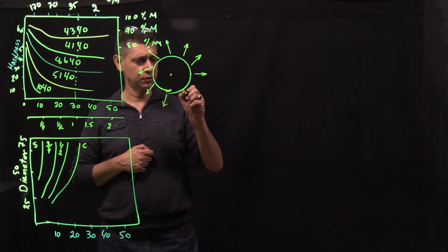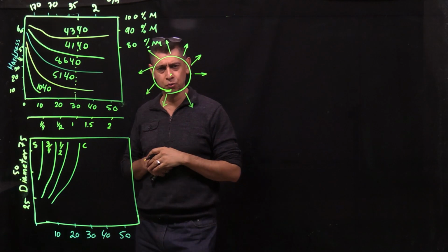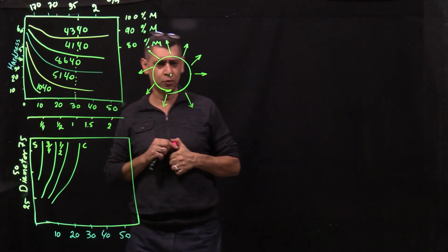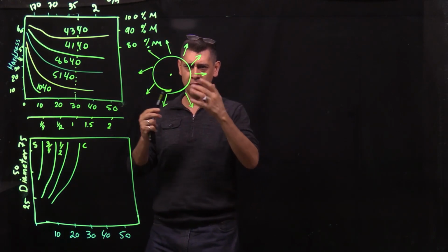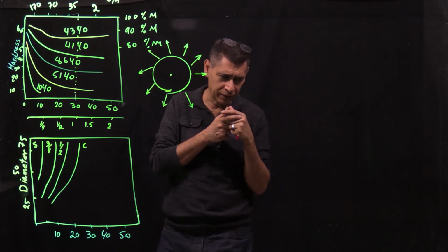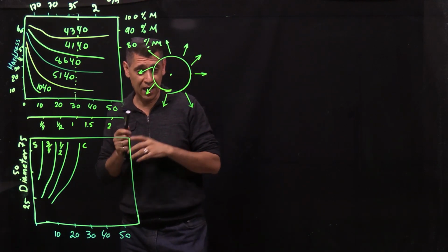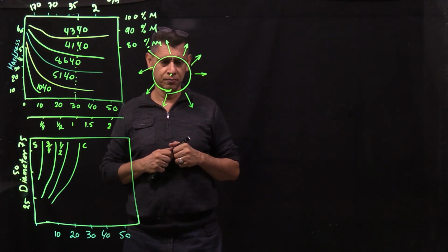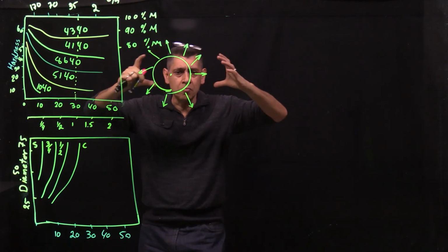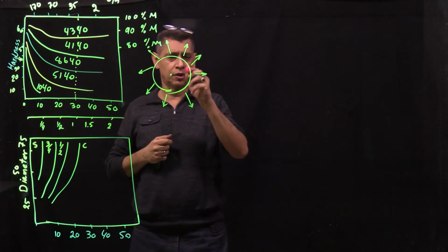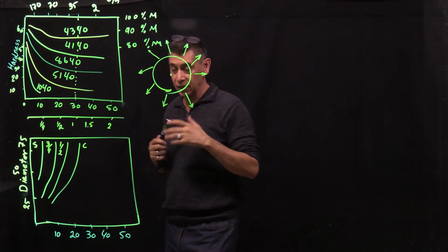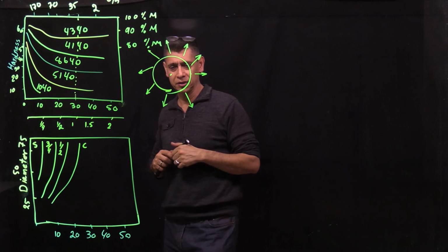And as a result, the surface has the highest cooling rate and the center has the lowest cooling rate. It is really important to know the regime of phase transformation, because ideally you don't want everything on the surface to become martensite, which has a volume expansion to get larger, and then the center starts to grow, and there is no room outside, so it's going to cause cracks. So you would like the center and surface to cool at relatively the same rate to get the same structures.